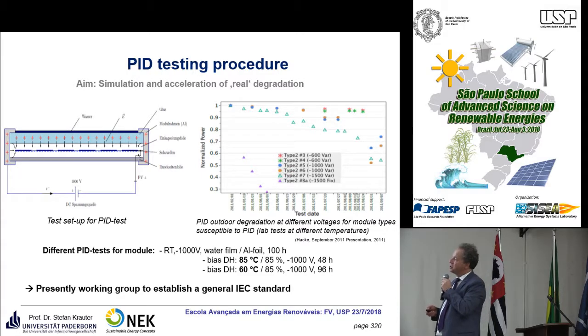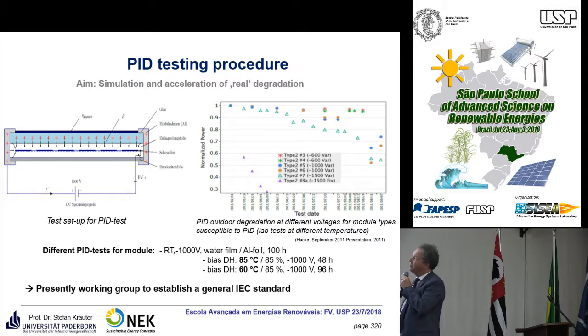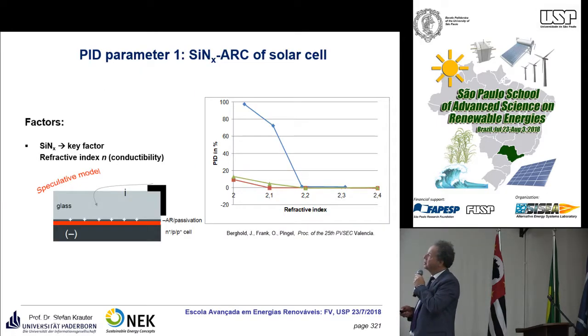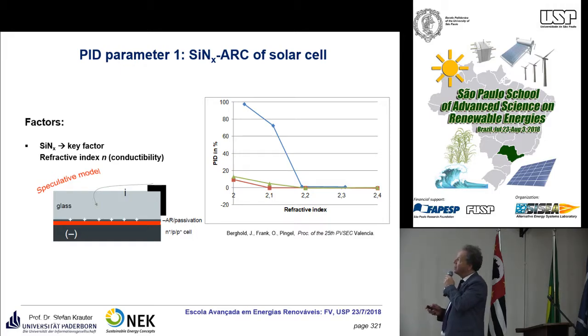So therefore we need some research at PID to find out test conditions at 60 degrees and 85 degrees. So we invented a test here, together with other institutes. Also this depends on the anti-reflective layer, the silicon nitride layer. So this is a function of the refractive index, so it depends on the nitride and the sodium content of the anti-reflective layer.